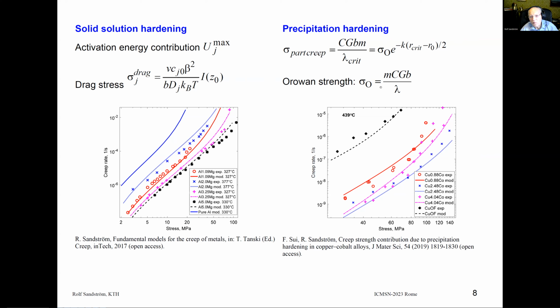Now, unfortunately, this overestimates the strength at high temperature quite a bit. Now, it's been assumed that you have to take into account the time it takes for the dislocation to pass the particles. And if you do that, you can derive a much better expression for the precipitation hardening. And here is an example demonstrating that it's quite possible to describe the influence of the cobalt content on this copper alloy, for example. It's also possible to describe the influence of temperature and other features.